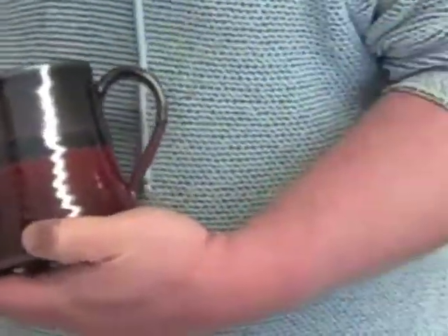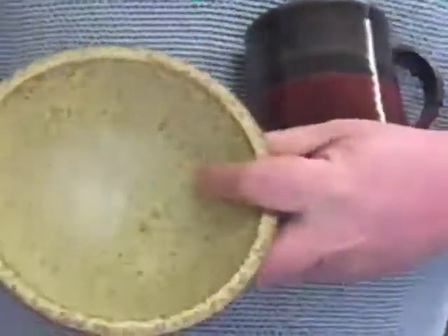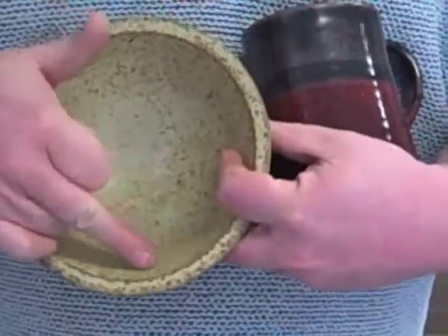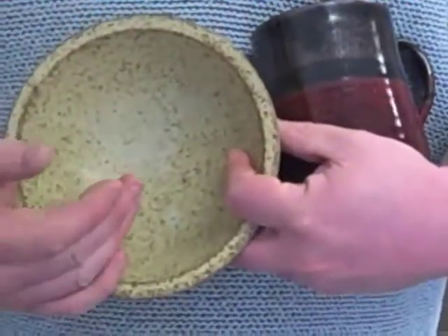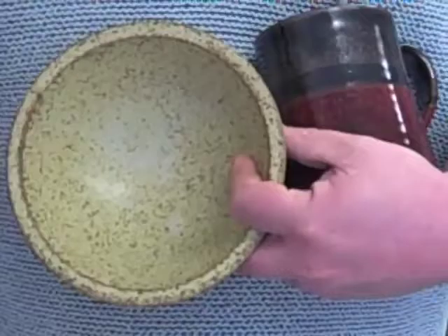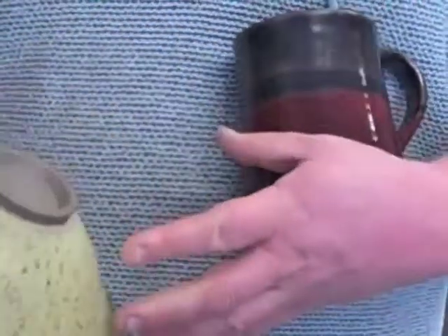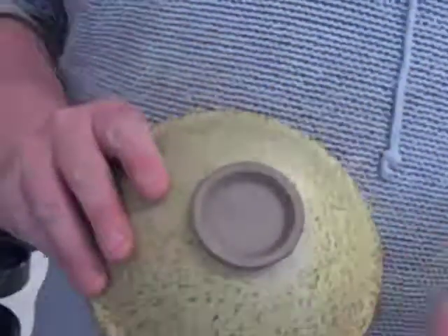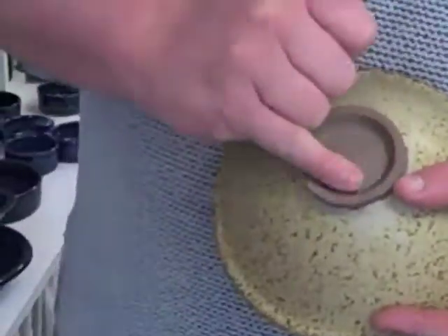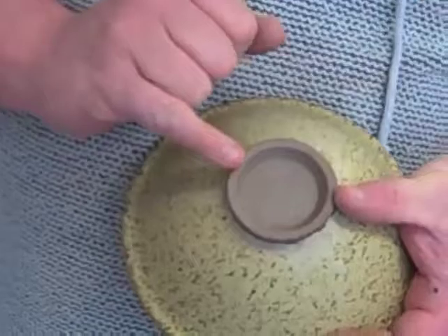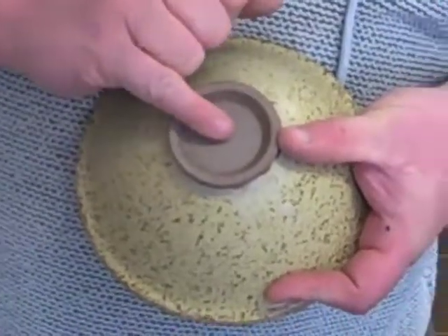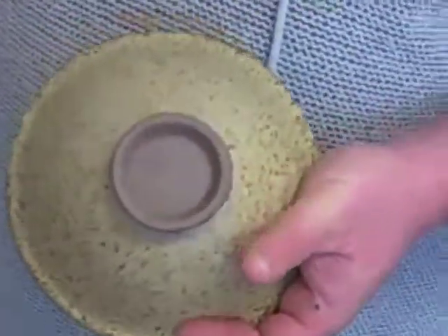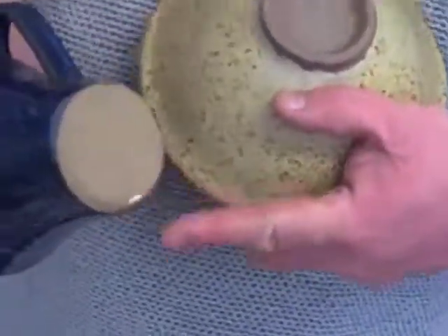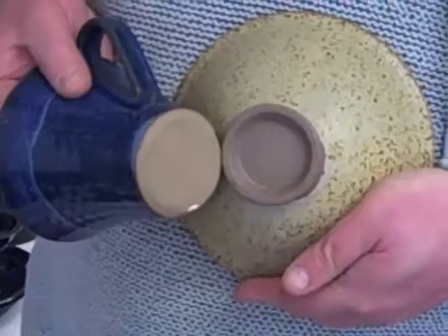Also, the iron in the clay comes through and you get speckles. That's the iron burning through the glaze as the oxygen is pulling it out. And if you look at the base of your pots, this pot here is quite toasty, dark looking, and that shows you that if you look at it very closely, you can see the little speckles of iron that have been brought out. Whereas in an electric kiln, you don't get that. It's a much paler look to it.